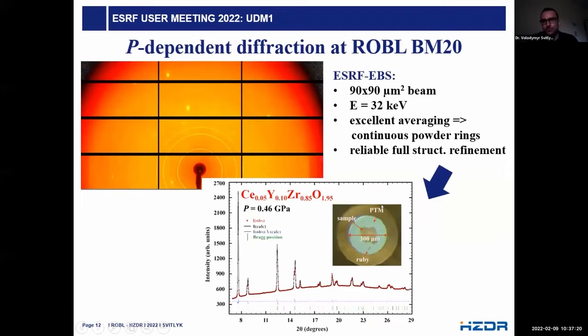From a technical point of view, the beamline was not designed for a microfocus beam, but thanks to the ESRF-EBS source, we are now able to focus the beam down to 90 by 90 micrometers at 32 keV. Because it's still quite large for the high pressure community, we are limited in pressure, let's say up to 20 GPa. But because of this beam size, you see this is actual raw diffraction data.